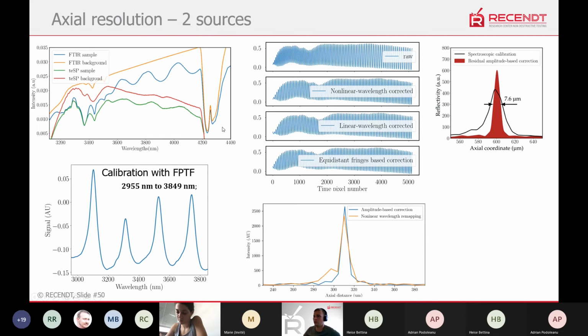Yeah, about calibration, as I said, I first used these features of polymers absorption and CO2 to calibrate the system, and it worked well. But further I switched to calibration with this Fabry-Perot tunable filter and used these peaks, which gives me a lot of points to make the calibration vector, which is slightly nonlinear, and as a result, I got the resolution of 7.6 micrometer.